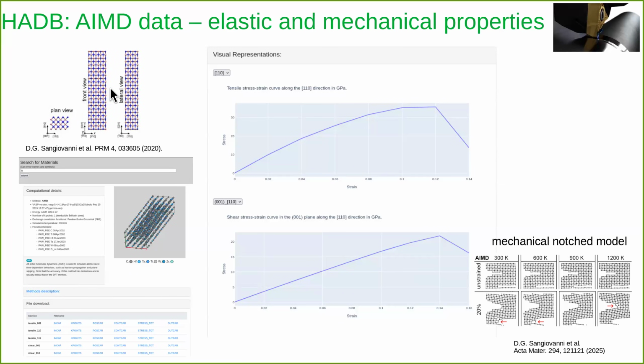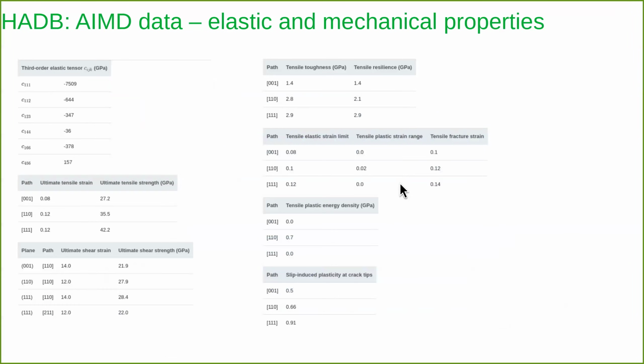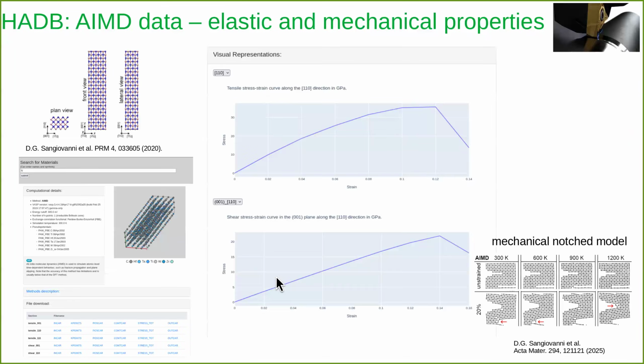Later on, we realized that this is a very ideal case, and then we started to develop a new stress-strain curve methodology, where we have an ab initio MD simulation with a notch model, which is summarized here. We are building in some type of notches, and then we open this crack to see what's going on and how the stress-strain curve is changing. That gives more realistic data for material scientists and nuclear engineers. And then we keep all the extracted information in the database, like third order elastic constants or the different strength values. The strength is actually just the maximum of this stress-strain curve.